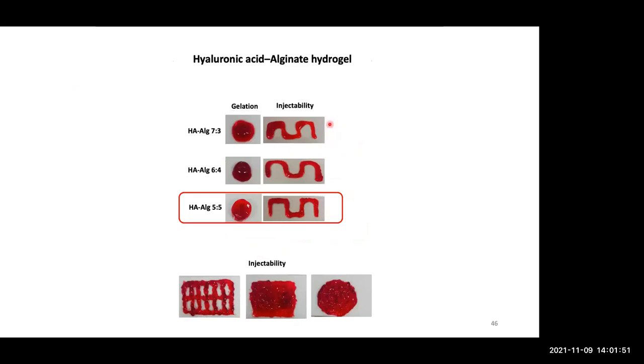Okay, and this is the picture from my lab. We try to develop the bio ink for printing the tissue. We use two different polymers. The first one is hyaluronic acid, the one that the cosmetic surgeon uses to make a filler, and we combine it with the seaweed polymer, which is alginate. We modify the chemical functional groups, so when they are separate, they don't become a gel yet, and then we combine them together. They develop covalent bonds and become hydrogels.